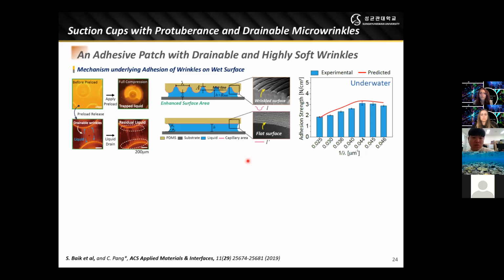And second, such micro wrinkles could induce an enhancement of surface area in capillary bridges. And we proposed a simple mathematical model to predict the adhesion strengths of the wrinkled patches on wet surfaces.